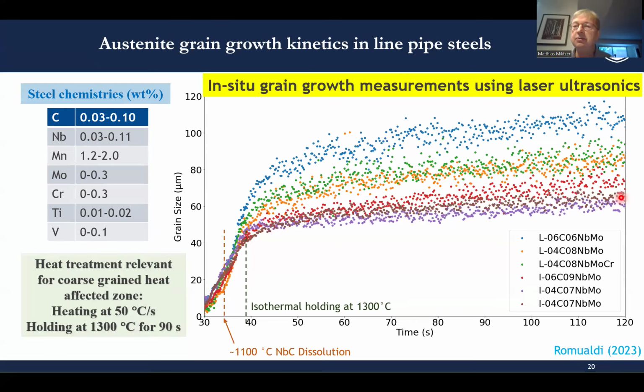What we see is quite a different range of the limiting grain size between maybe 50 and 100 micrometer. And we have here steels labeled with L. These are laboratory produced steels, so they are ingot cast. And then with I, these steels are industrial produced, continuously cast. And this obviously has an important impact on the titanium nitride particle distribution. And we get finer titanium nitrides in these industrial produced materials. And have confirmed this also with scanning electron microscopy studies.